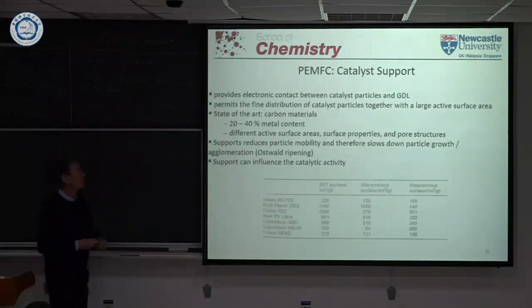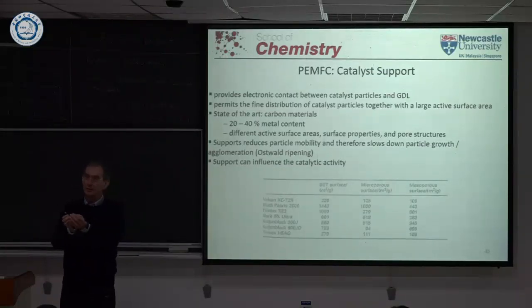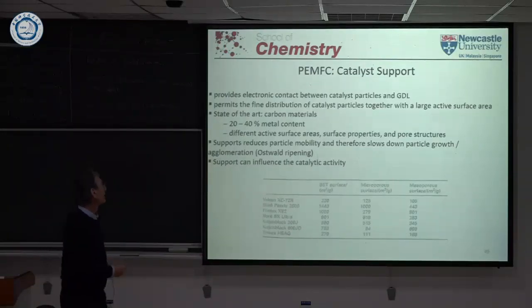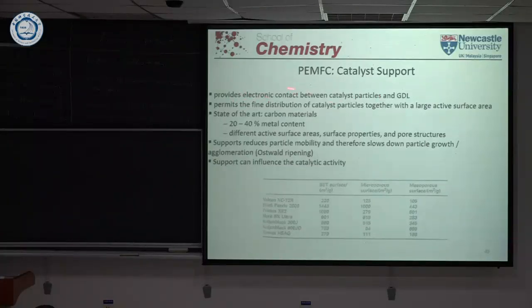Now, the catalyst support is typically that you use carbon particles, let's say they are about 100 nanometers, 200 nanometers diameter, and then you put catalyst particles of a few nanometers onto the carbon particles. And the important aspect is that you provide the electronic contact between the catalyst particle and the GDL. At the same time, you get a fine distribution of the catalyst on the carbon itself and make a large surface area. And then there are different criteria that are used in the fuel cell that you call the weight percentage. It's how much catalyst you have on the carbon particle. And for different reactions, this plays an important role, how high the weight percentage is, if you use hydrogen or you use other fuels. So that needs to be typically found out.